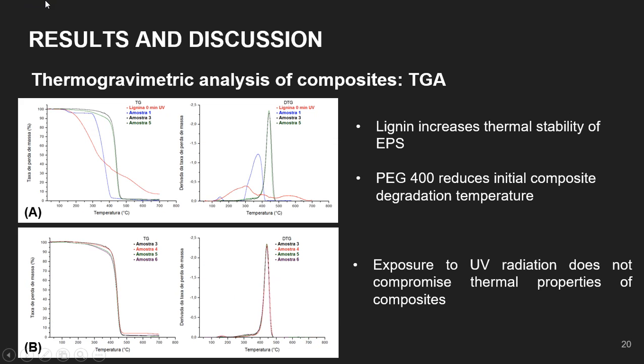Regarding the thermogravimetric parameters, Figure A shows the TGs and DTGs obtained from lignin as well as from pure EPS and composites. In this, the increase in the degradation temperature provided by the incorporation of lignin in samples 3 and 5 is evident. When comparing these two samples, it can be seen that sample 5 undergoes the initial degradation at a lower temperature than sample 3.